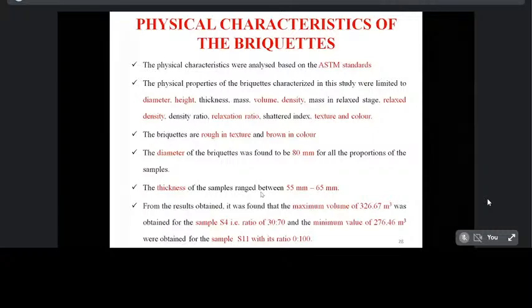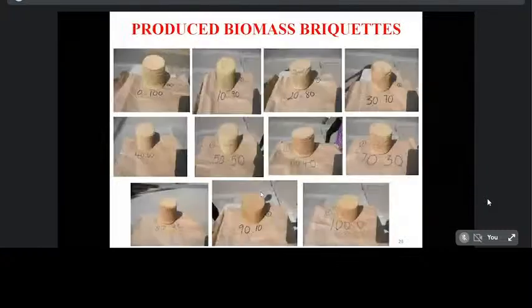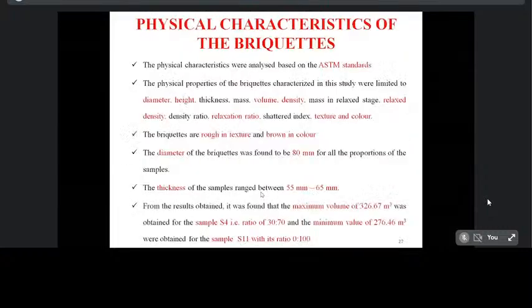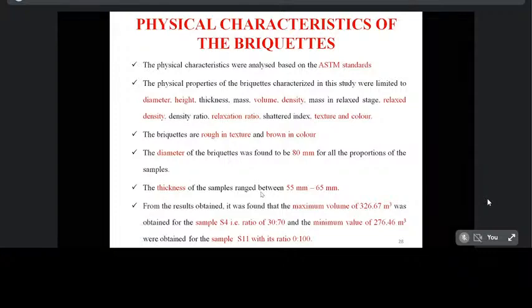So the briquettes we have seen in the previous image. Okay, so this image shows the briquette is rough in texture and brown in color. So the diameter of the produced biomass briquette was found to be 80 mm because the cylindrical mold diameter is 80 mm. So the produced biomass briquette also has 80 mm diameter for all the proportions of the samples. The thickness of the sample ranged between 55 mm to 65 mm.